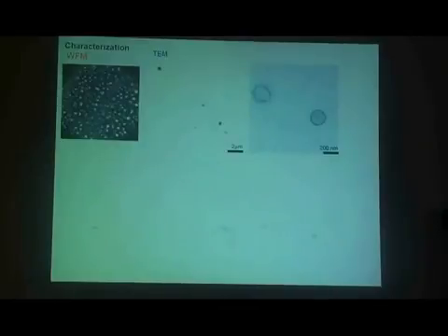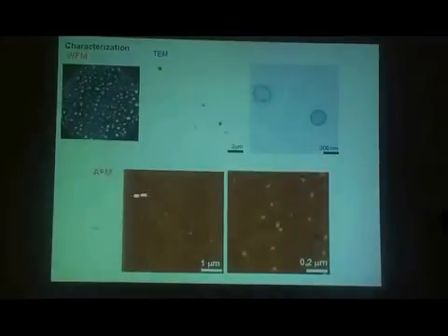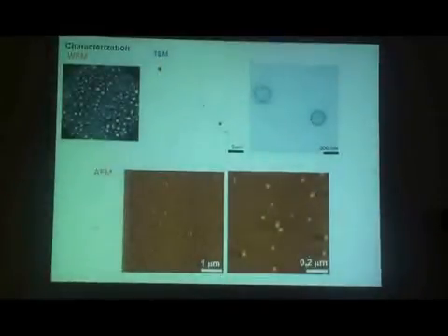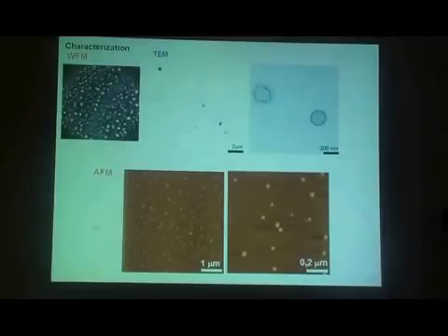One is that it is really a ring-like structure, or it could be a hollow sphere and you are monitoring only the ring. In order to understand that, you need AFM, and when you do the AFM, you don't see any ring-like structure but instead you see spherical structures. This is possible only if it is a hollow, or what you call vesicular, structure. So that is how you characterize that.